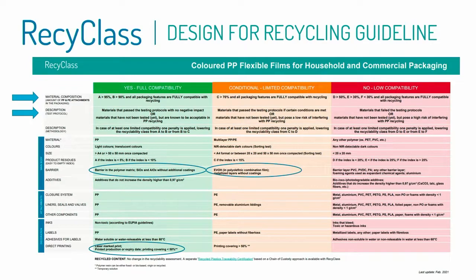I would like just to focus on a few design features, talking about flexibles. First of all, barriers that are quite important for flexibles. In particular, I would like to point out that EVOH seems to be today still the most promising barrier. We have tested already barriers in polyethylene. We are currently testing EVOH as barrier in polypropylene flexible, and probably we will define a threshold value for the use of EVOH as barrier in polypropylene flexibles.